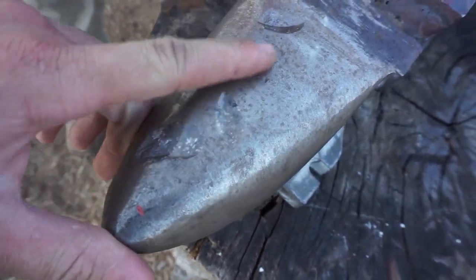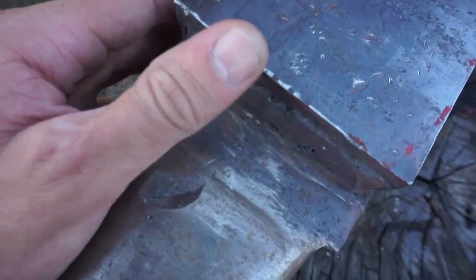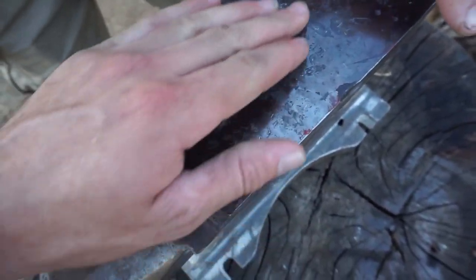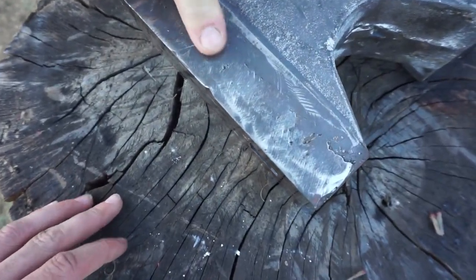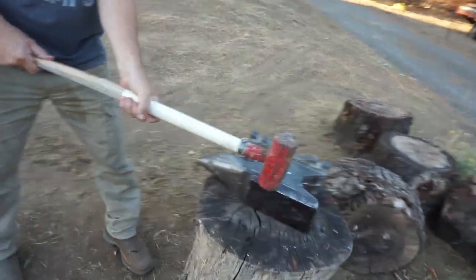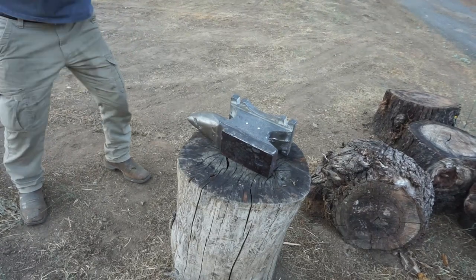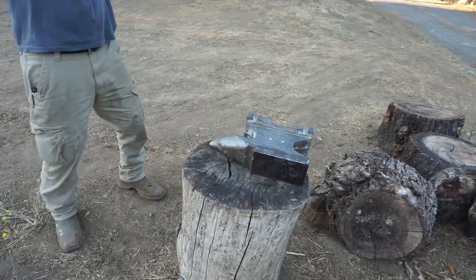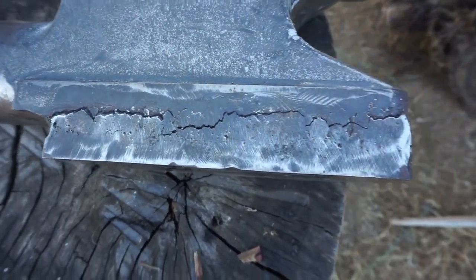It's a soft cast iron, just dense like crazy. With the A2, where I got it on the edge it dented — we knew this thing wasn't perfectly hardened, it was a little bit cold when we hardened it. Still harder than the cast, but yeah, not quite as hard as it should be. The welds haven't split yet.